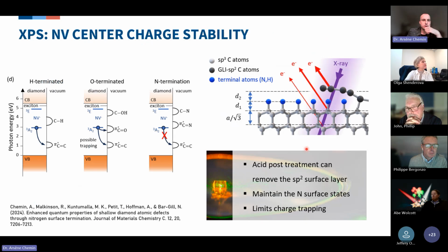That is very interesting when we look at the NV defects, because the NV defects lie here in the band gap. If you have a lot of sp2 defects, or some oxygen bonding at the surface of the diamond, those actually lie below the NV states, and so you can have charge trapping happening. That can lead to the blinking that we were discussing in the introduction. In the case of nitrogen termination, this problem is way less important because the CN states are slightly more up in the band gap, so the trapping is less important.